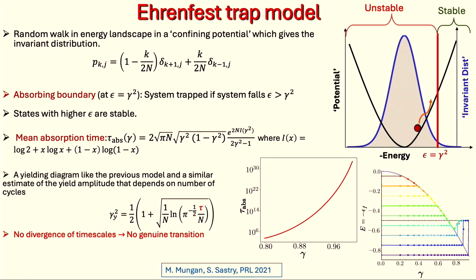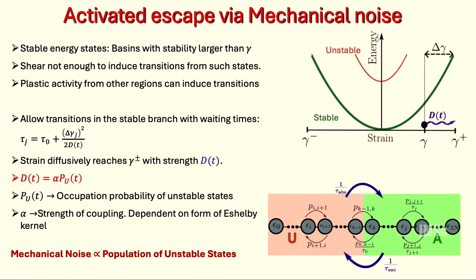So that's what we look at next, which is even if I have this random walker in a confining potential and it reaches an absorbing state, the absorbing state is not permanent. It can escape out of it. Then we have to ask, what is the mechanism for you to escape out of it? And the mechanism is what I mentioned earlier, which is the stress kicks that the system might experience because of activity elsewhere in the solid.